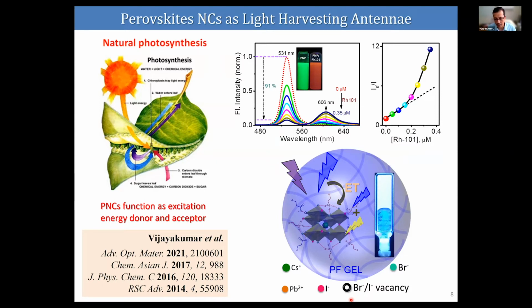And when we incorporate these materials with suitable emitting polymer matrices, we can even prevent the halide ion migration. This is one of the major issues in these perovskite materials, because they can show halide ion migration and the properties will go bad under excitation with light. And we can actually prevent this halide ion migration in these systems, and we can generate very efficient white luminescent materials out of this. And we published this work in Advanced Optical Materials this year.